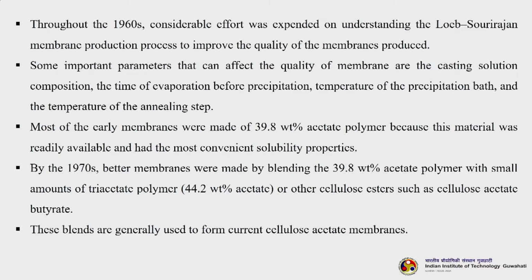Throughout the 1960s, considerable effort was expended on understanding the Loeb-Sourirajan membrane production process to improve the quality of the membranes produced. Some important parameters that can affect the quality of the membrane are the casting solution composition, the time of evaporation before precipitation, the temperature of the precipitation bath and the temperature of the annealing step.